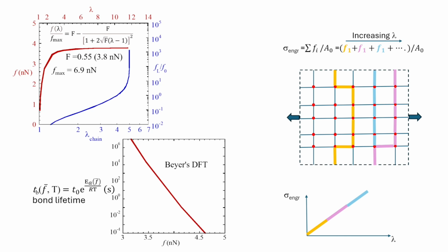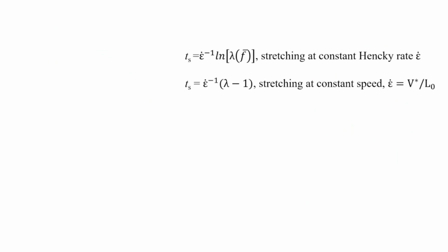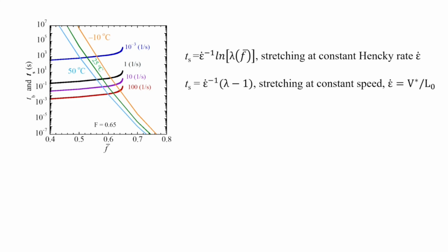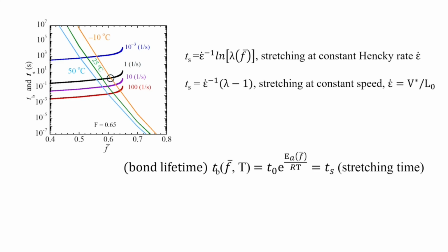At the end of the day, if you read what kind of force is in the tension corresponding to how much you stretch, you can have a sense of what the bond lifetime is, because reading the force gives you the bond lifetime. So separately, when you stretch, time elapses, you spend time doing it. It's a matter of drawing how much time it takes versus what's the bond lifetime. The whole secret is this bond lifetime matches the time you spend stretching.